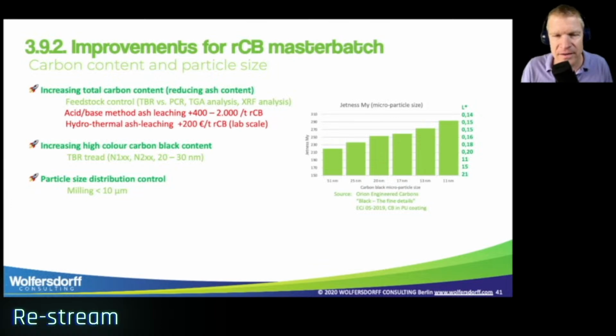Of course, we can correct the ash content after the pyrolysis, but as a chemical engineer and process engineer, my experience is the earlier you correct for any kind of problems, the cheaper it is and the more efficient the method is. So there's an acid/base method for ash leaching, and depending on how much carbon content you're happy with, if you want to have 98% carbon, you might add some 400 euros variable OPEX cost to the process. If you want to be 99.5 and higher, you're certainly adding 2,000 euros per ton of the recovered carbon black. And also, if you think about the large volumes of recovered carbon black in a typical plant, thousands of tons, if you have to run all these through an acid and a caustic, this perhaps has also some safety